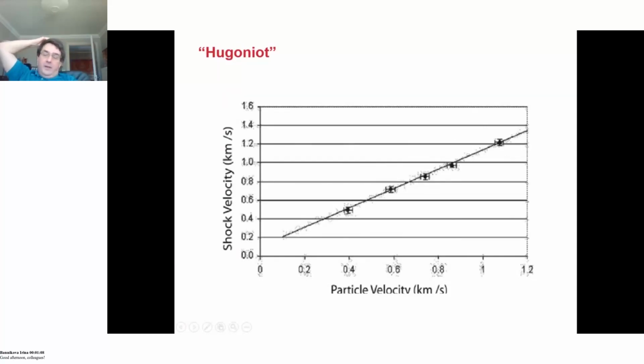Here's the particle velocity. Now, what you will notice here is the slope. If I look here, I see 0.4, and about 0.3 here. And actually, if I draw a line from 0,0 up to this point here, I will get fairly close to all of that data. So in fact, it's not showing a detached shock wave. What it's showing is the particle velocity and the stress, or the shock velocity, if you want to call it that, are basically the same.